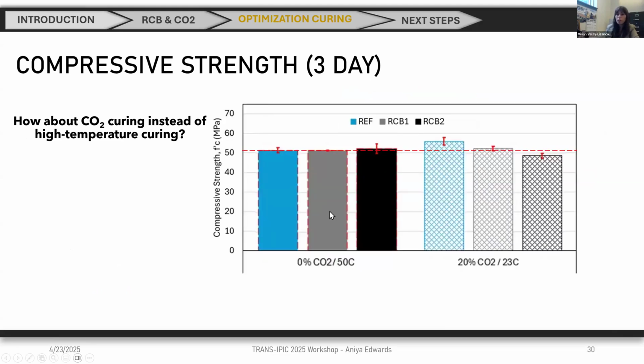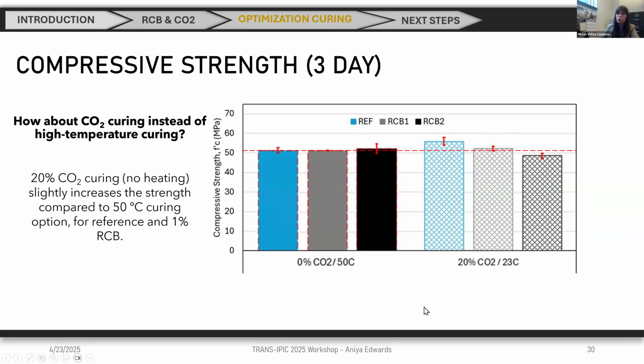So how about comparing CO2 curing with no CO2 curing but high temperature curing? Here are some of the results. Here you have 0% CO2, so we are not doing CO2 curing, but we are doing high temperature curing, compared to 20% CO2 curing. And we can see that we have the same or even slightly better results when we have CO2 curing, no heating, than heating. So CO2 curing looks like a great option to not need to heat. So it's an alternative option, I would say.